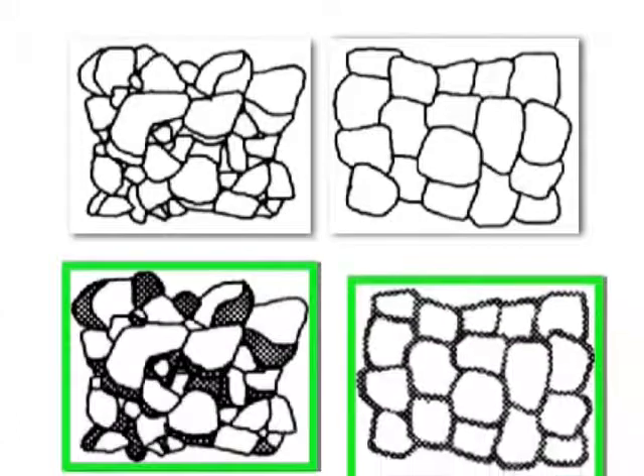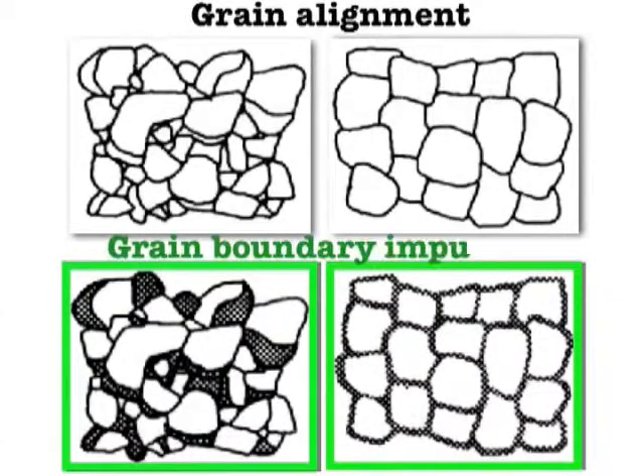Take combinations of rare earth elements, for example NEG, neodymium europium gadolinium barium cuprate, that will give you very high irreversibility properties at 77 Kelvin, but also there's some evidence to suggest that grain boundaries are less likely to form if you have this combination of elements.